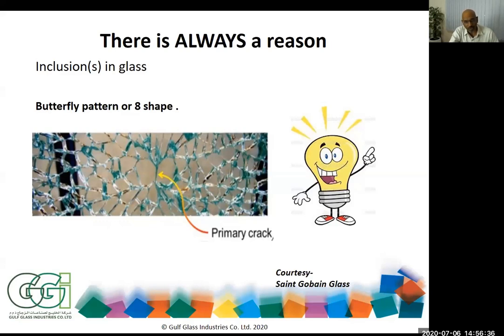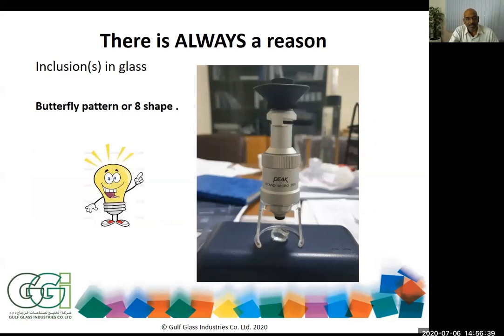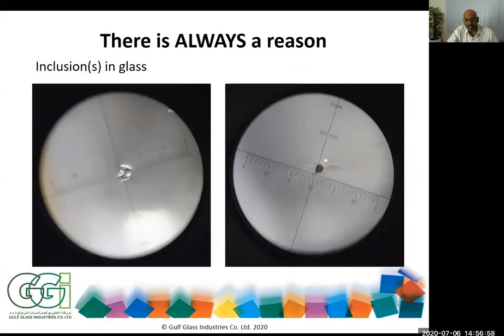So what should we do when we see something like this? At GGI, we pick up the glass, we try to analyze it. This is a 25 magnification microscope that we use to identify if there is an inclusion in that butterfly pattern. What we found is these two photographs that we have taken from this microscope of 25 magnification. You can actually see one of the inclusions is shiny and the other one is probably dark brown or gold in appearance. Can we tell that it is a nickel sulfide inclusion?